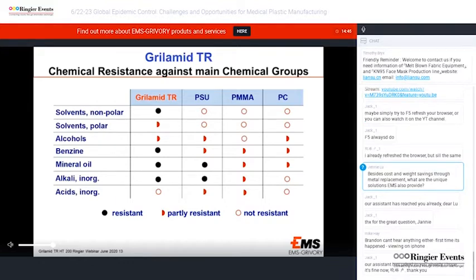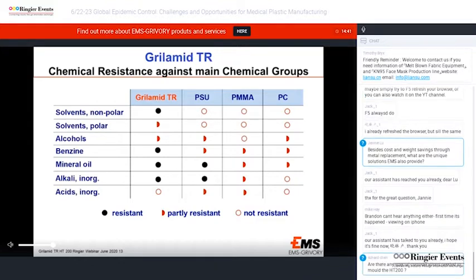If we start on the right hand side, we see that polycarbonate and acrylic have relatively poor chemical resistance, not really showing any good resistance against the main chemical groups. The polysulfone is considerably better, however has problems with solvents. The transparent amorphous grade with the best chemical resistance is Grilamid TR, which overall shows a very good resistance, with the only Achilles heel being acids.